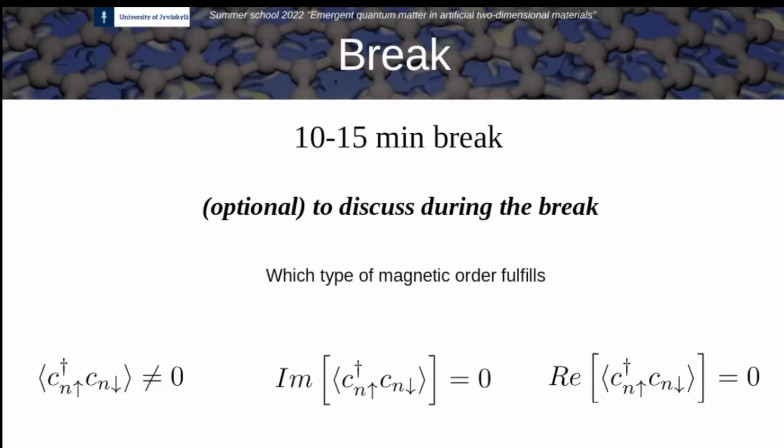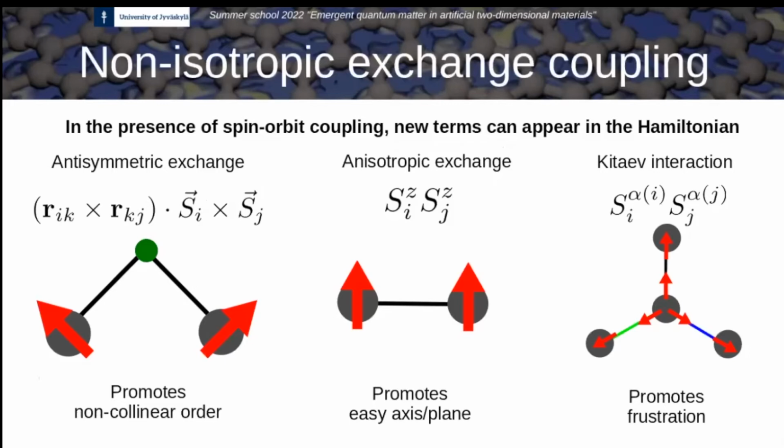So it can come both from geometry or it can come from the Hamiltonian itself. For example, in the triangular lattices and in Kagome lattices, the geometry itself gives you frustration. Exactly, it's not always like that. For example, this term, the Kitaev interaction, appears in a honeycomb lattice. This is a lattice that is bipartite and doesn't have any problem with the geometry. But the frustration comes from the term itself, which tries to align a spin in three different directions that are incompatible at the same time.